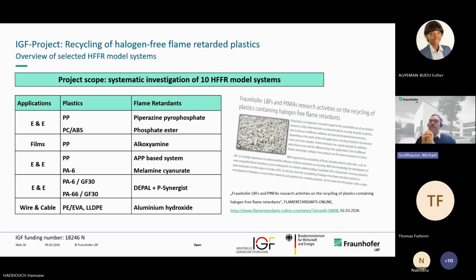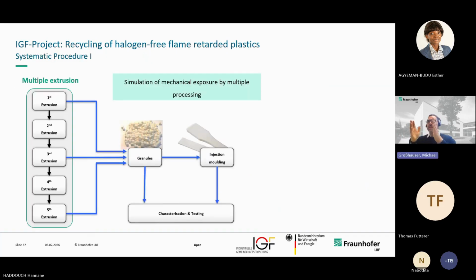And next slide, please. And here you see the first systematic procedure. So we did multiple extrusions to look inside the material, what's happening if it will be reprocessed. So we took out material from the first extrusion step, the third extrusion step, and the fifth extrusion step. Then we got granules out of that. We made characterizations and testings out of the granules, of course, but also we did injection molding and tested those injection molded parts.